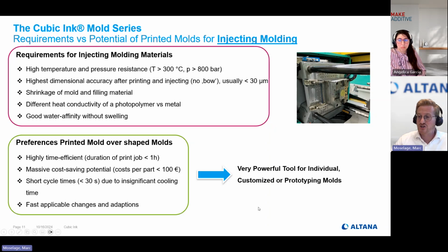And changes you need to make in the mold can be done very, very quickly. You can adapt this quickly. For example, if you need to change any properties, if the shrinkage of the polymer is not well predicted because your geometry is very complex, it's not so easy to do this on a metal part. You can shape away more metal, but you cannot add metal to a shaped mold. And for a one-shot mold, you print a new one with the specific requirements. So actually, a lot of benefits.